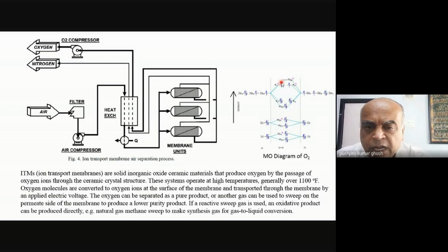Now, what actually it does is that you have these modules. These are actually ceramic membranes. You have to use ceramic membranes because polymeric membranes would obviously not withstand these kinds of temperatures, whereas ceramic membranes will. So you have got ceramic membranes, and these ceramic membranes are ion transport membranes. So applying an electric field across these membranes under those temperatures and in the presence of the electric field, the O2 becomes O2 plus, and then the O2 plus permeates on this side because of the electric field. And of course, your electron, which you lost at this point, that electron can flow into the other side. And so at the permeate end, your O2 plus can again become O2.